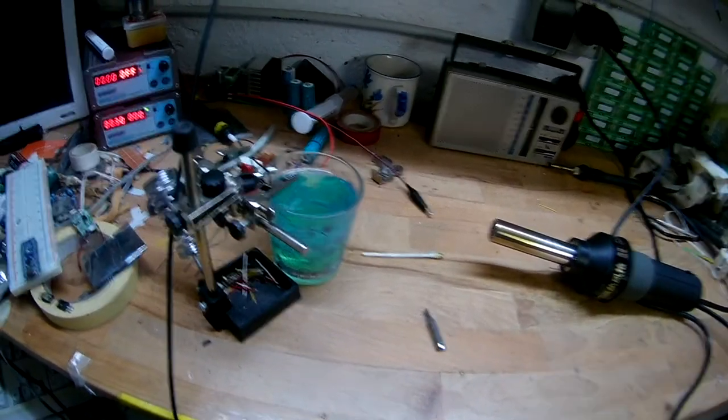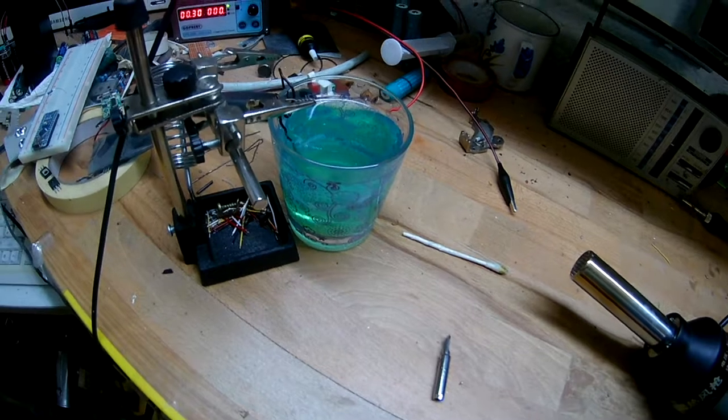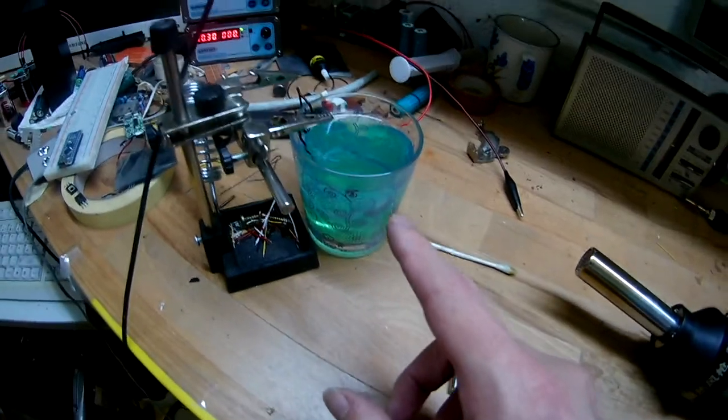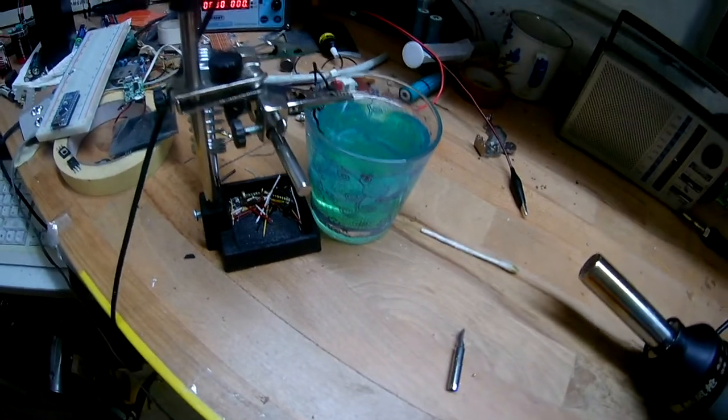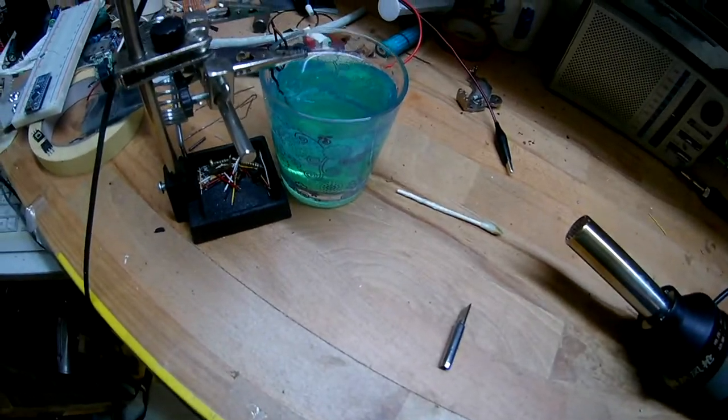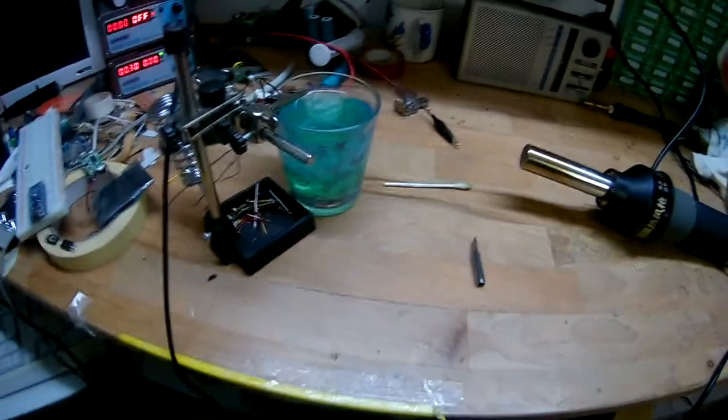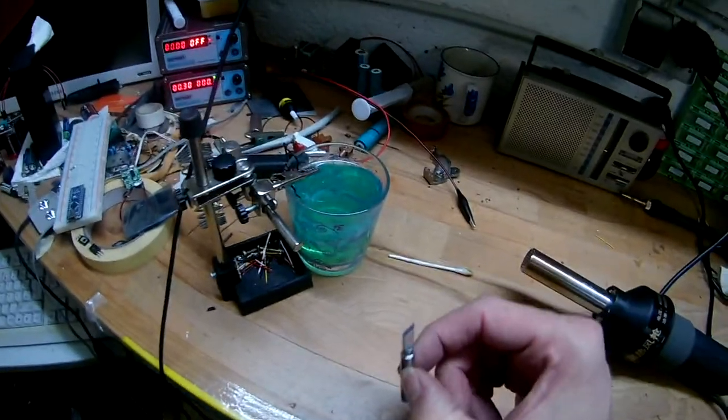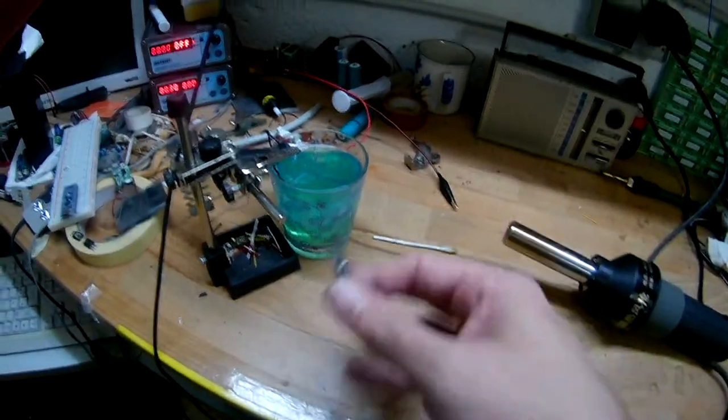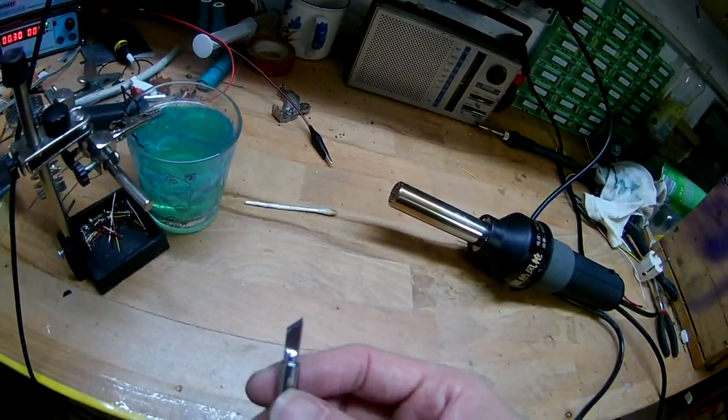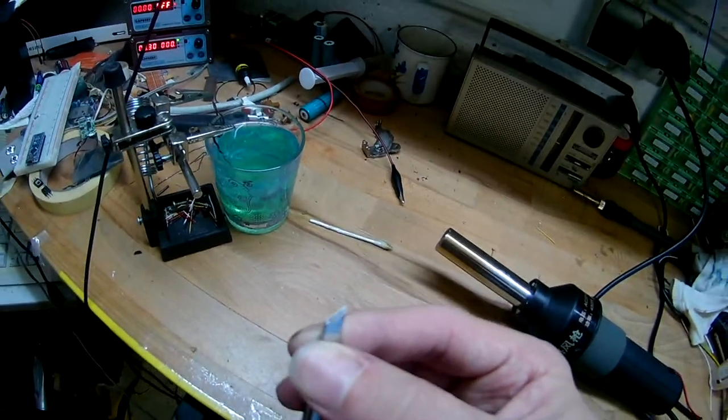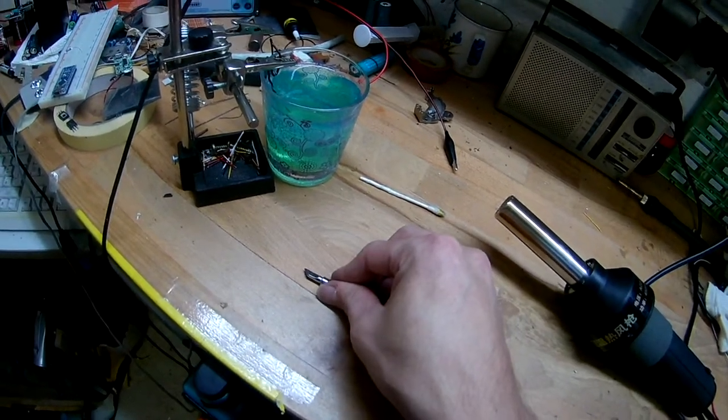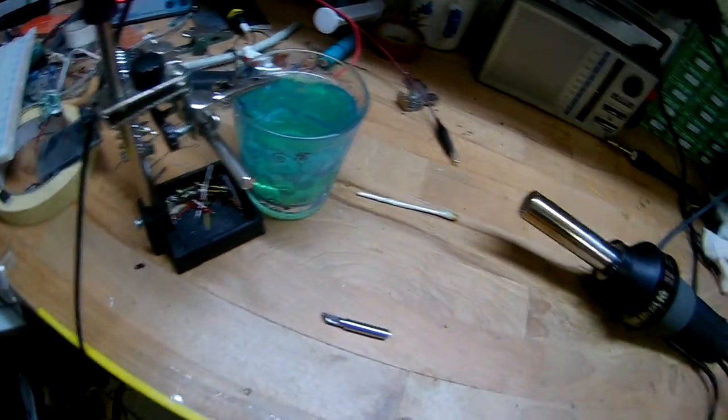And in this case, well, I don't have a super sophisticated electroplating bath here. That's just water out of the tap with copper sulfate in it, which is like, I mean it's not that bad but it's bad. Basically usually you have to put some acids in there too, which I don't have, and some other chemicals which I don't have too. I don't want to buy them, I just want to get a bit of copper onto some surface. I didn't just buy that thing just for this, no, I tried to copper plate things before, it didn't work too. But now I found a post about how the copper ions can't carry a higher voltage difference or voltage potential difference, which kind of explained to me why it was just going black all the time.